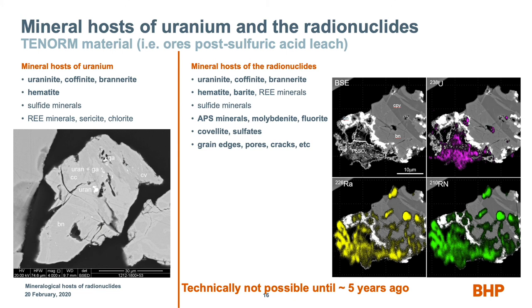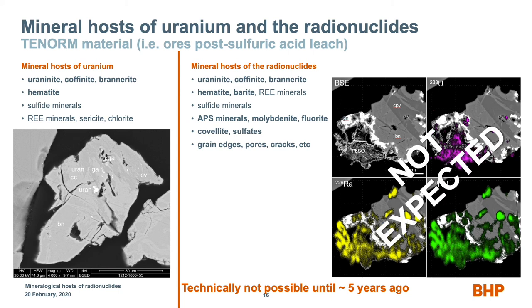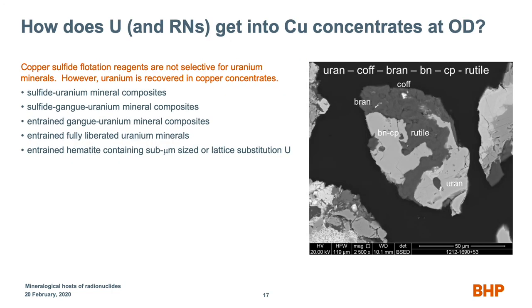So let's actually look at a picture. This is a chalcopyrite bornite grain, and it's kind of ratty here. The bright stuff around here is some lead, it's galena, but there's lead sulfate, and that lead sulfate was a former uraninite that actually got dissolved away. We can look at the U-238 on here, and we see there are little hot spots in here, but there's still a little bit of uranium that's surviving after that leaching process. But again, we look at the radium and the lead-210 and polonium-210, and there is overlap with that uranium-bearing spot, but then there's a lot of it someplace else. And the someplace else is because it occurred during concentrate leach, really. It's the remobilization that's going on. Game-changing. Again, not expected. We were hoping, but not expected.